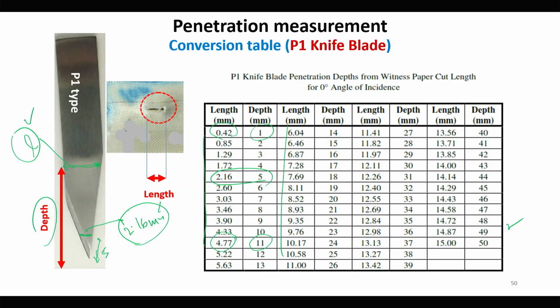So, here as per the standard, we should have below 20 millimeter, but effectively we can measure the depth up to 50 millimeter.